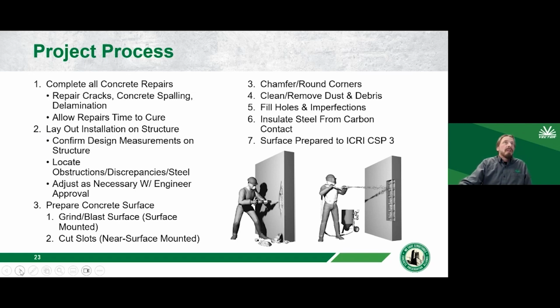Oftentimes we don't typically have full access to the FRP repair or installation area. We know that we need to strengthen some beams, but we may not, in the development process, have access to all the beams. Once we have access, we want to confirm the measurements match what was designed. If there are any discrepancies, it's typically not too big of a deal. Get back to the FRP designer and say, hey, there are some differences in measurements here. What do we do? It might involve doing some different detailing of the FRP installation itself, or adding some FRP. And we're typically very conservative in that early on in the process.